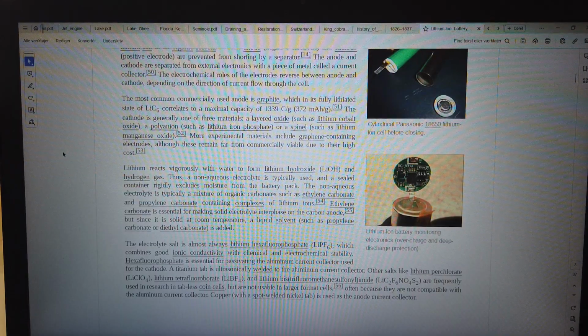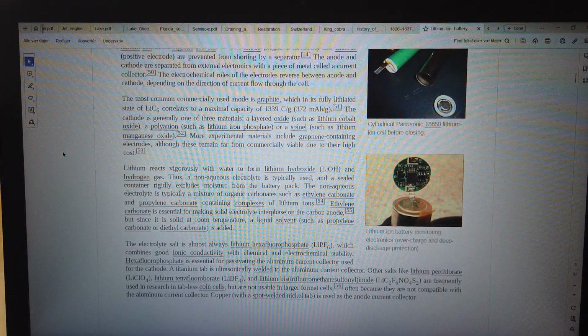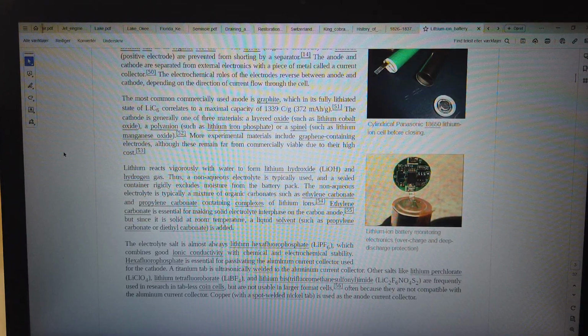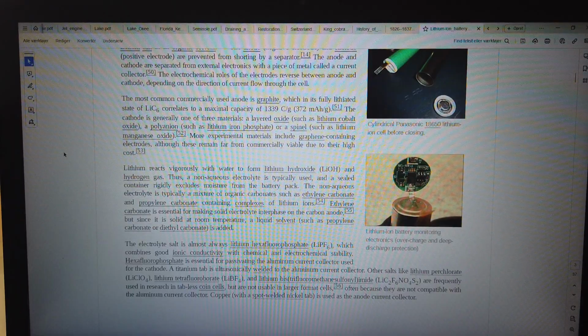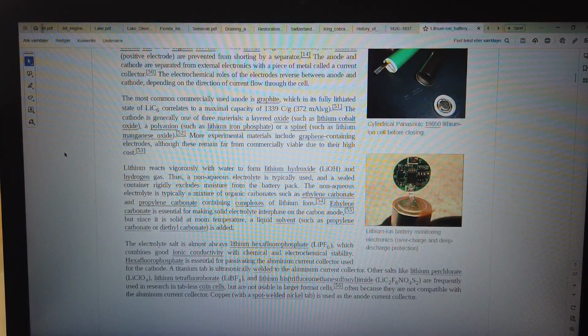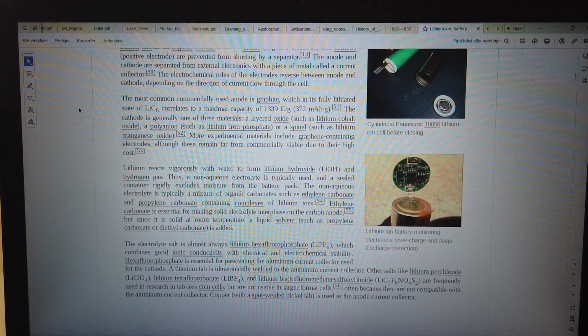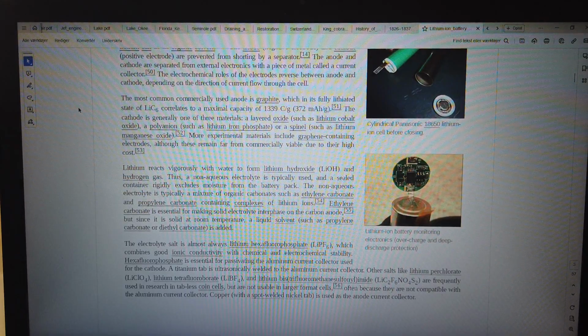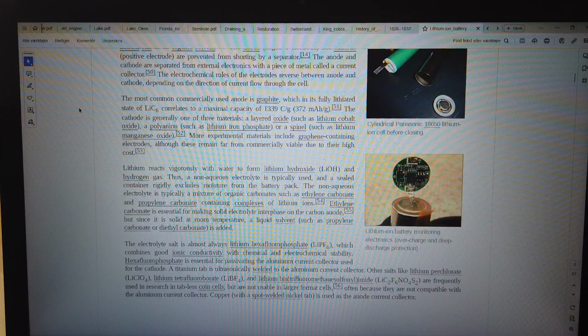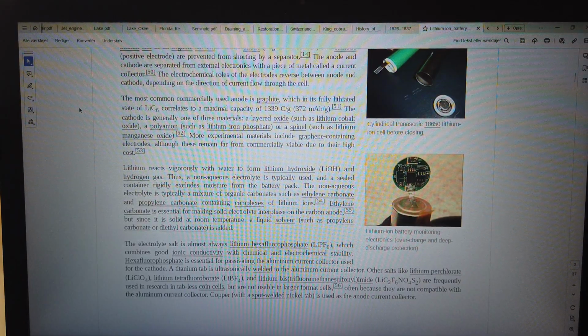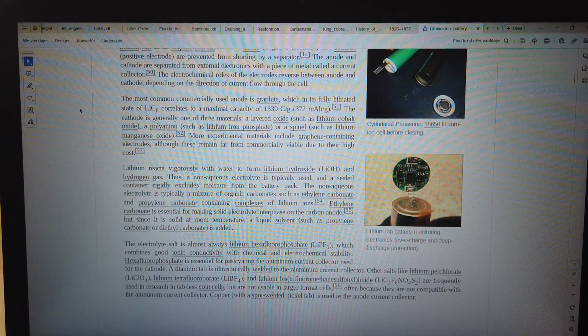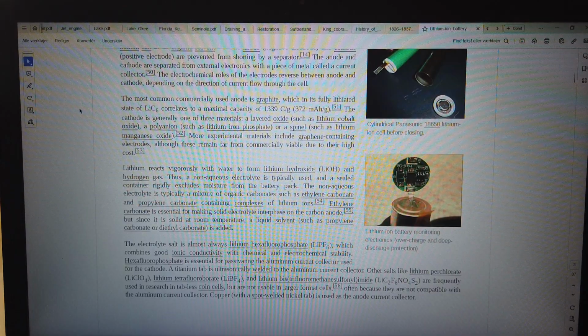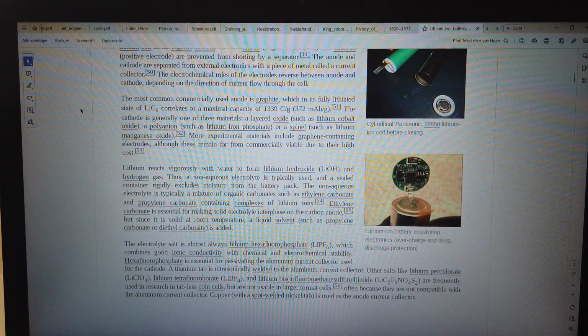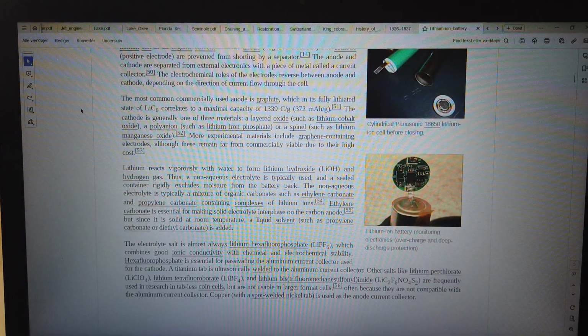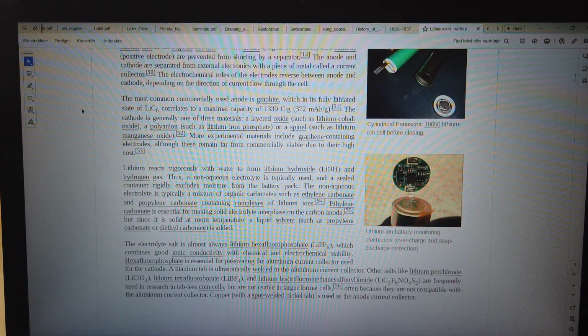53. Lithium reacts vigorously with water to form lithium hydroxide, LiOH, and hydrogen gas. Thus, a non-aqueous electrolyte is typically used, and a sealed container rigidly excludes moisture from the battery pack. The non-aqueous electrolyte is typically a mixture of organic carbonates such as ethylene carbonate and propylene carbonate containing complexes of lithium ions. 54. Ethylene carbonate is essential for making solid electrolyte interface on the carbon anode. 55. But since it is solid at room temperature, a liquid solvent, such as propylene carbonate or diethyl carbonate, is added. The electrolyte salt is almost always lithium hexafluorophosphate, LiPF6, which combines good ionic conductivity with